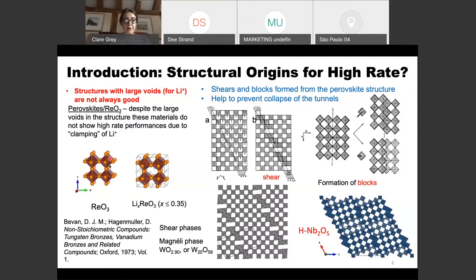For people like myself as solid state chemists, one of the obvious materials to look at are perovskites or so-called rhenium trioxide structures, which are like a perovskite unit except there's no cation in the center. In principle, you've got a very large space to allow the lithium ions to move within. But one of the problems you have with this type of structure is that if the cation is not the right size, the units will rotate and they'll clamp the cations in place.